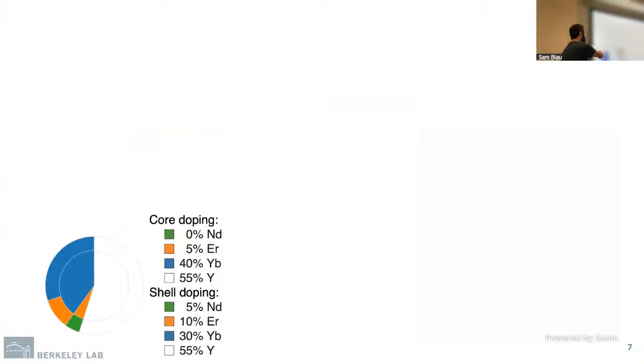So this is a representation. I'll be using not a machine learning representation, just a graphical representation to depict a nanoparticle with different thicknesses of regions and different amounts of doping. So I'm not saying that all the ytterbium is over here. I'm using this as a pie chart saying that the core is all homogeneously 40% ytterbium, 5% erbium, and then 55% host material. And of course, the radii are depicting the thicknesses of the regions, right? So just pie charts, but within a region, you are homogeneous.